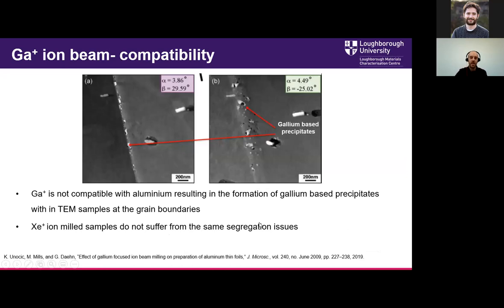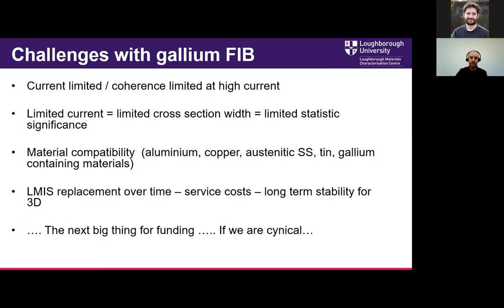There are some other advantages to moving towards xenon. Gallium isn't necessarily compatible with materials like aluminium. So if we wanted to do TEM sample preparation with aluminium, we'd often find that you can form gallium-based precipitates inside the TEM sample. And so you start to see things that aren't really representative of your material of interest. And xenon eliminates these issues. You don't have the same segregation issues in materials like aluminium.